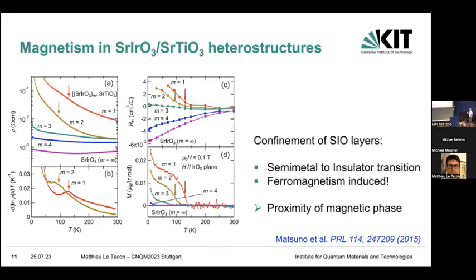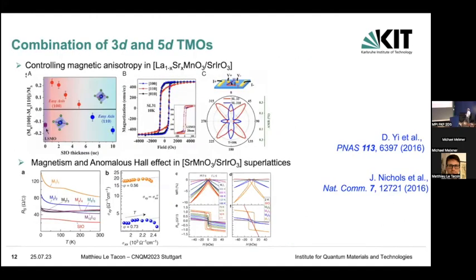So there is the proximity to a magnetic phase here, which has been further explored in combination with other 3D compounds, in particular with manganites, where by introducing some layers of iridate, you can control the magnetic anisotropy and the magnetization of metallic manganites. Or you can even observe an anomalous Hall effect in superlattices. Sorry, that's not strontium here, it's lanthanum strontium. So that's really in the metallic compound.